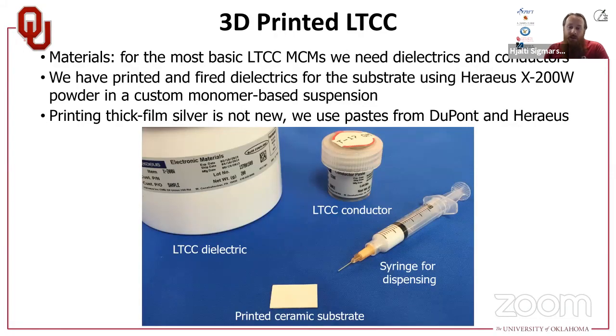So what we've done here is we started off with some materials from Heraeus, and we had this X200 powder that they make tape out of. So we just went and sourced the raw materials from them, got the powder, and put that into a liquid suspension that we made using a monomer with some dispersant, and we mixed it up pretty nicely. And then we put it in a syringe and we dispensed it, and we were able to create relatively decent sized boards. These are about 50 mil thick, if I remember correctly. So we printed them, and then we sintered them, and we also took just regular LTCC conductor paste and printed that on top as well.